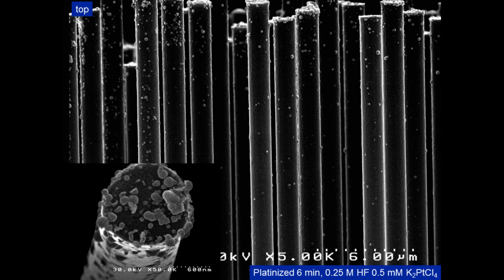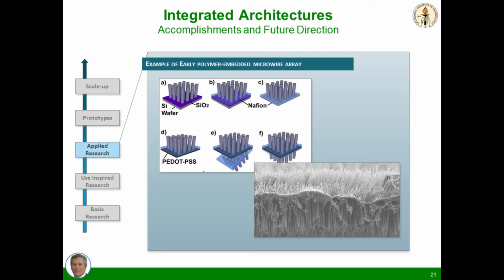But that isn't the whole system, because that silicon can only reduce water to hydrogen. It can only provide us about half of a volt, and we need at minimum 1.23 volts, as I said, to split water by the first law of thermodynamics, and practically you need more than that because you have overpotential losses and resistance losses. So we can't do it even with two pieces of silicon, but we wanted to show we could make the structure anyway. So we made this full structure by, instead of doing expensive epitaxial growth, we made it like making a driver's license. We peeled an array, and then we did it again, peeled another array, except that we add a little bit of baloney in our sandwich equivalent.